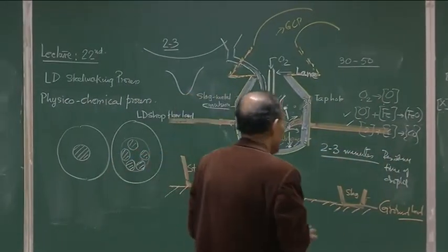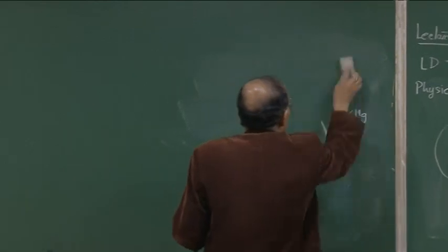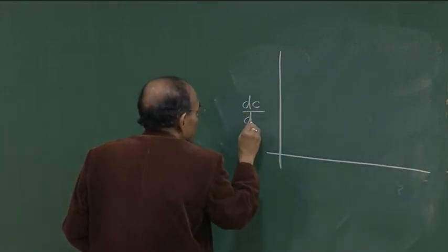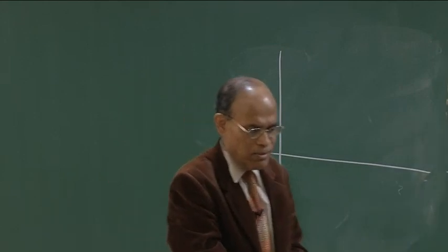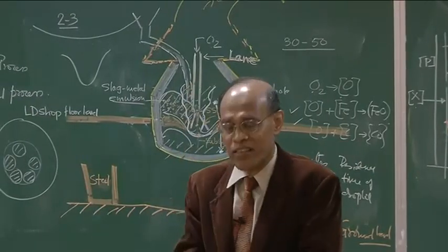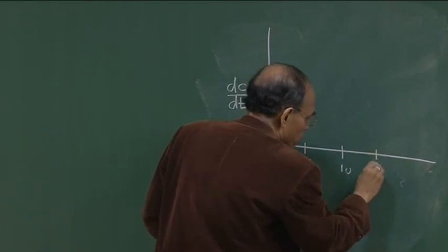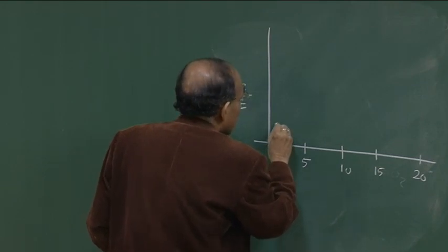And where does the knowledge of end point control come from? The end point control information is hidden in the decarburization graph. These are all going to be plant specific. Every converter, depending on its blowing practice and design, will have a characteristic decarburization graph, but nonetheless the general trend is going to be the same. If you have 5 minutes, 10 minutes, 15 minutes, and then 20 minutes, then we will see that the decarburization graph schematically can be,